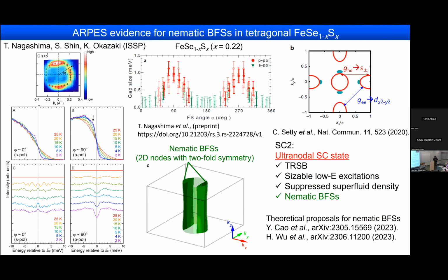Okay, so then I asked the laser ARPES people. This is the data taken by Okazaki-san in ISSP, and we provided samples in the SC2 region. And they found that in the normal state, they can find a C4 symmetric Fermi surface, which is consistent with the tetragonal crystal structure. But if you go into the superconducting state, if you look at this 90-degree Fermi surface around here, they see a clear opening of the superconducting gap. However, if you look at 0 degree, which is around here, they don't see the opening of the superconducting gap.